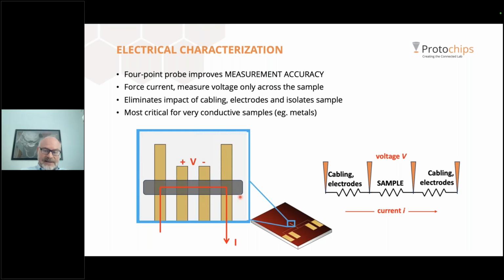So the 4-point probe technique involves the sample spanning 4 leads as shown here. Current is forced through the outer pair of leads and therefore through the sample, the film, and voltage is measured on the inner pair. This approach improves accuracy because the added resistance of cabling, connectors, the electrodes on the chip, and the contact resistance can all be factored away, leaving only a very accurate measurement of the sample itself. Now, this is most important for conductive samples like metals or low resistance semiconductors, where the added resistance of the system is a substantial part of the total resistance. If the sample has many mega ohms of resistance, then this technique is less important. At that point, to be honest, good sample prep is probably the main issue. I'll talk about that in a second.